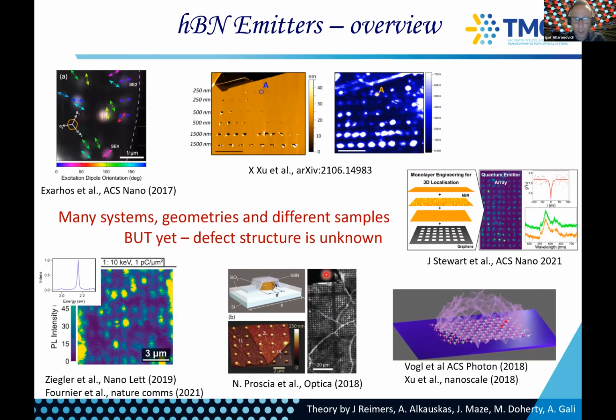There were some works done by putting hBN onto pillars, plasma-based systems. There was a very recent work from the group of Stephen Hoffman to irradiate or to anneal large hBN material and then kill some of the emitters with graphene that has apertures inside, and that creates this type of nice arrays. You can also make indents with an AFM, and also some approaches for ion implantation work. So many different systems, and the defect structure is of course still unknown. And so that is how we started.